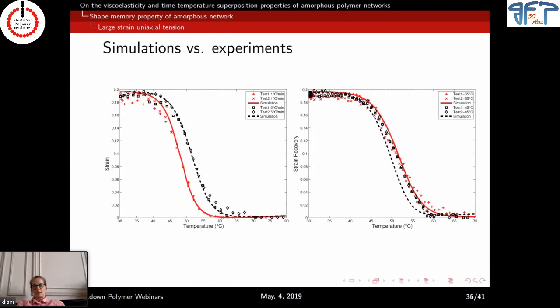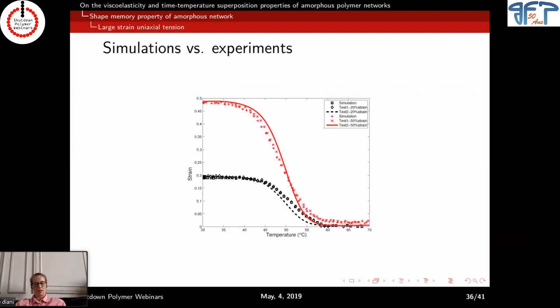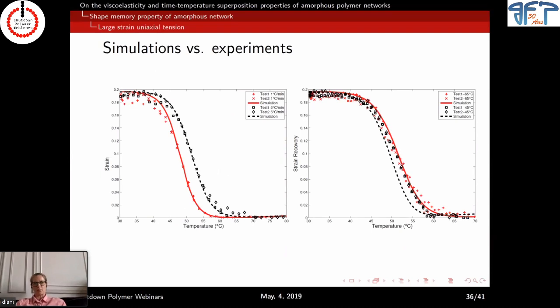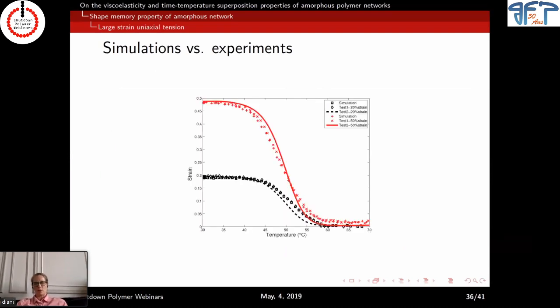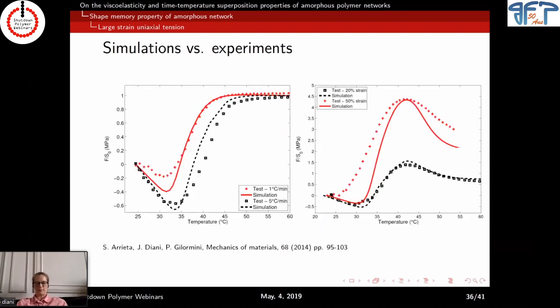So with the same model, you can see that we have a very good prediction of the shape recovery, whatever the temperature rate, whatever the applied maximum strain. And also we were able to show that we get very good stress recovery. So the constitutive equations are robust enough to not only look at how the shape recovers, but also how the force evolves with temperature.